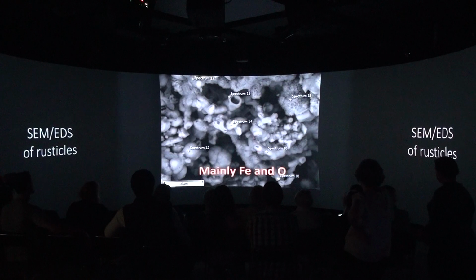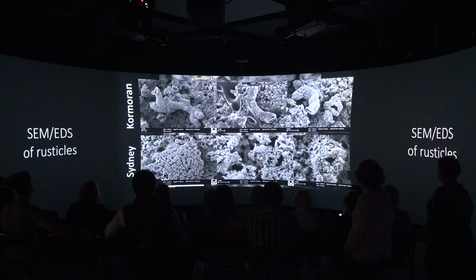These little tubes that Laura was presenting in her images resemble Proteobacteria, but you can see other types of structures. You can see pom-poms, you can see spherical structures, and they are mostly composed of iron and oxide. And we could also see a difference between the microstructures in the Sydney and the Kormoran. The Kormoran had more of these tube-like structures, and the Sydney had more cigar-like iron oxides with some cavities, but